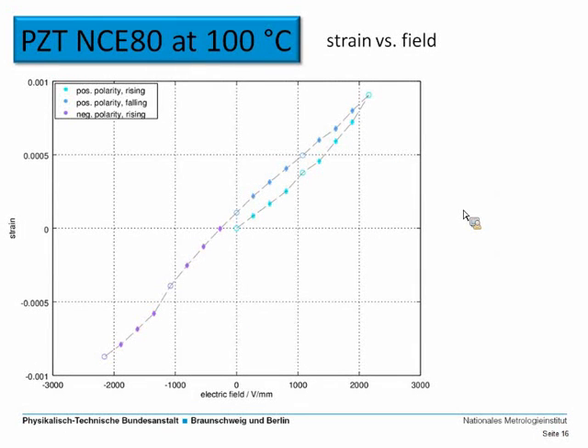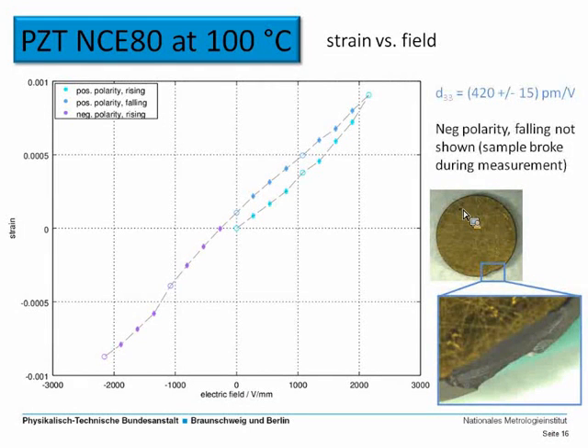Again, the same plot as strain versus field, so the same information. From the positive polarity part again, you can calculate the D33, which yields a value of 420 picometers per volt, which is larger than the room temperature value, but it's not really surprising. We don't have any value to compare it to because Noliac doesn't supply that, but we can still measure it.